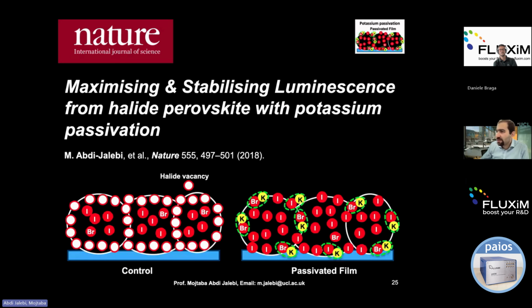So what we have done here is, as I mentioned, halide vacancies, which are mostly accumulated at the grain boundaries, are the major problem. This is a simple schematic that shows how we came up with the idea of adding potassium iodide into our system to maximize the luminescence efficiency. This is a cross-section of the perovskite thin film, and it shows that we have a lot of vacancies at the grain boundaries. These white circles show halide vacancies. By adding potassium iodide into the system, we are filling these vacancies with the extra halide we are introducing.